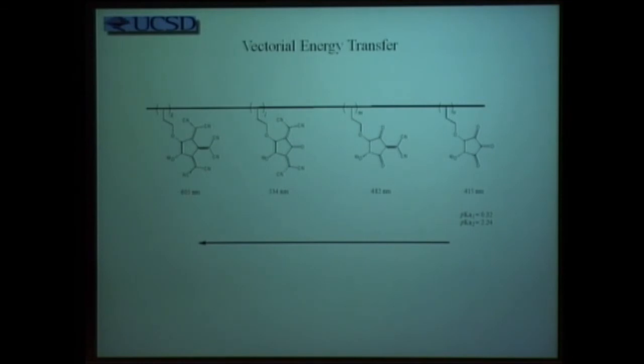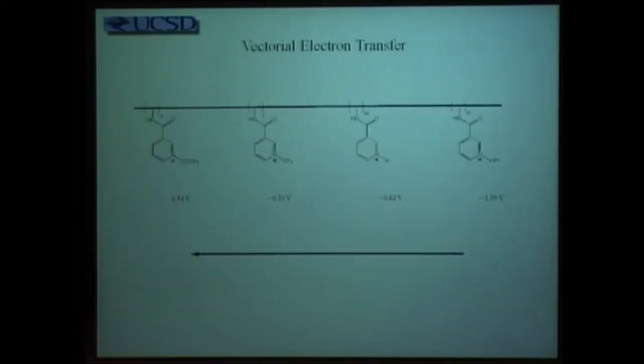This is much like what plants do in trying to collect and allow excited state transfer to proceed. We can do the same thing with electron transfer. So once again, you see derivatives of a common reagent. The numbers below each one show the reduction potential. And it means that if you had a reduced species, they would all migrate to the left as you're looking at them. So in other words, it's possible to make materials that have multiple chromophores arranged in a well-defined way that can be used to absorb a large fraction of the solar spectrum.